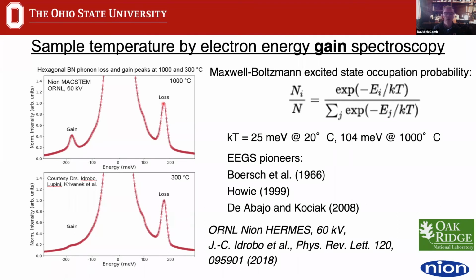In other words, the fast electron here should not only be able to lose energy, it should also be able to gain energy. And indeed, you can see, because of the energy resolution that they were able to achieve here, is the peak associated with the energy gain. But the ratio of the intensity of these is then given by this expression, which is basically our Maxwell-Boltzmann expression for excited state occupation in this system. And therefore, you can use this to actually then determine the temperature of the specimen.